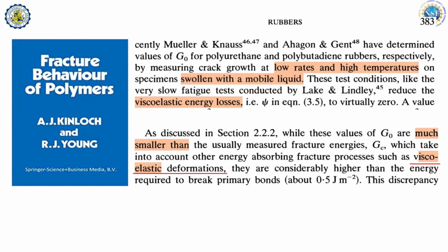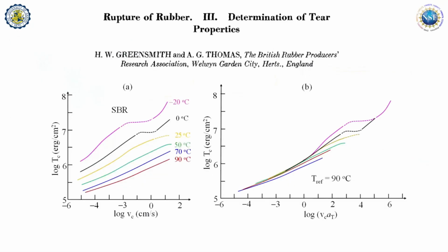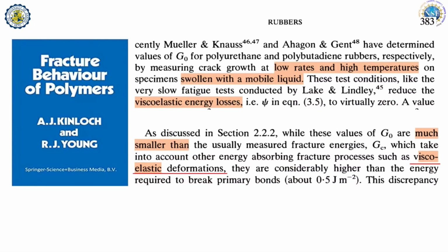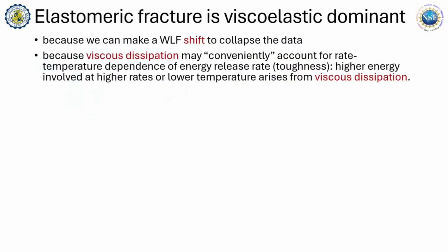Well, nevertheless, it seems that we thought we found the way to think about it. Ignore the fact that the shift is not perfect. We're in a hurry wanting to suggest that this is all there is, that the temperature effect is just about viscoelasticity. It's just about polymer dynamics. So let me summarize. Supposedly, fracture is about viscoelasticity. Why? Because I can do a shift and collapse my data, not perfectly, but I can.